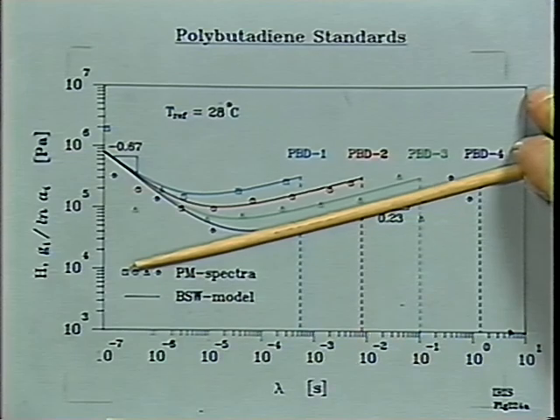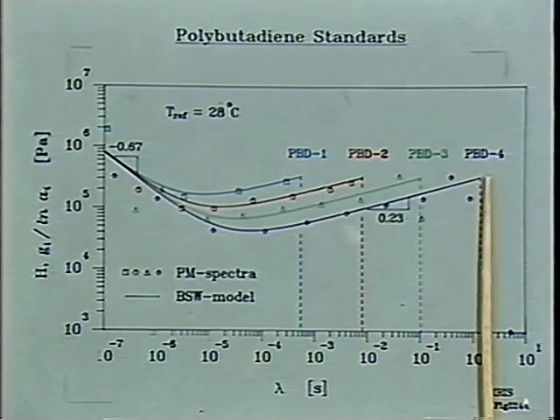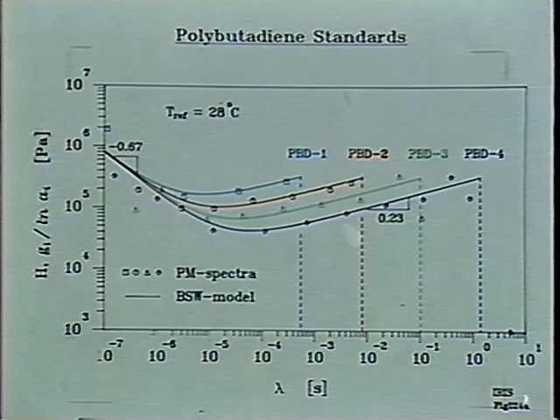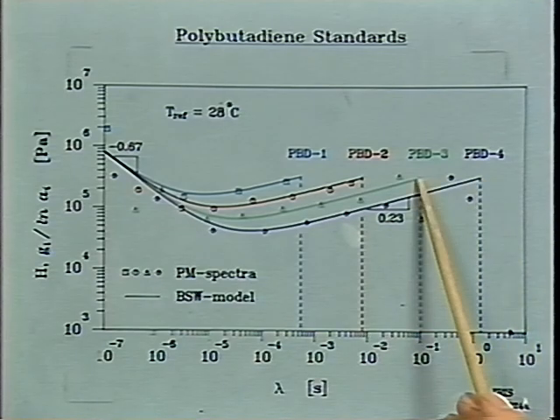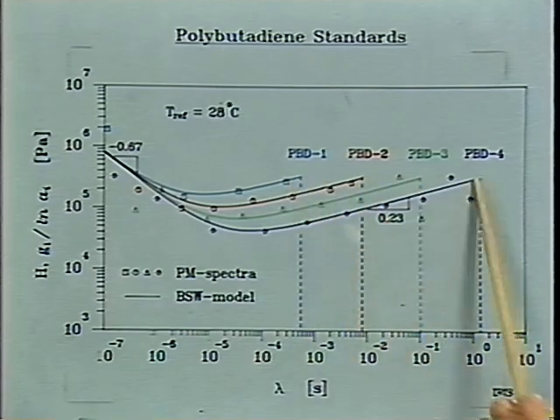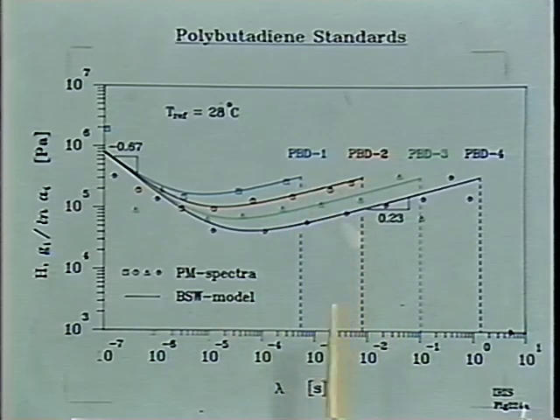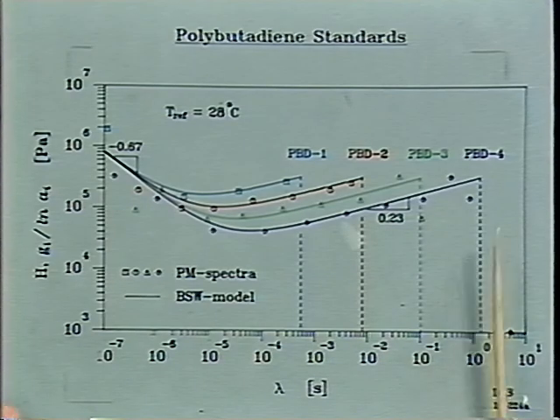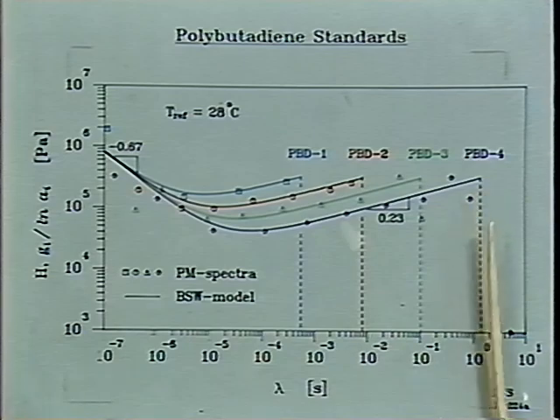This is h of lambda, and it was cut off at the longest relaxation time. You can see that the highest point is constant, independent of molecular weight, expressing the plateau modulus being independent of molecular weight. And the cutoff is proportional to the molecular weight to the 3.4 power. And that type of spectrum we wrote down just for this linear region.